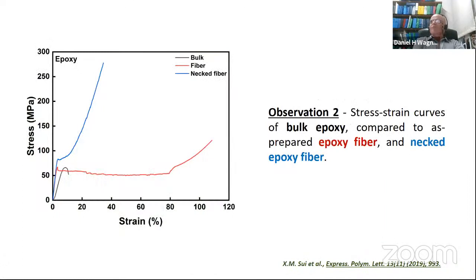Now, no less impressive and surprising is the stress-strain curve. Bulk epoxy is in black here. This is the typical stress-strain curve of bulk epoxy. As you see, it reaches around 60 megapascal, as I said, 60, 70, and the strain goes up to 15% or 12% or 10%, something like that. But now the fiber we prepared is in red. This is the fiber we prepared. The modulus is higher, as you can see from the slope here.